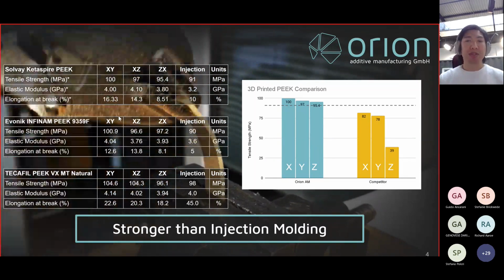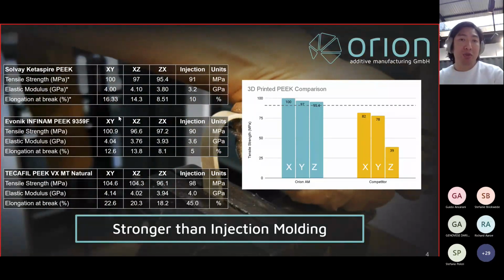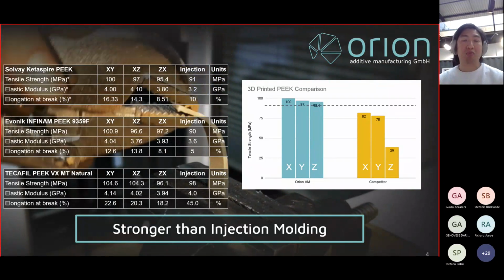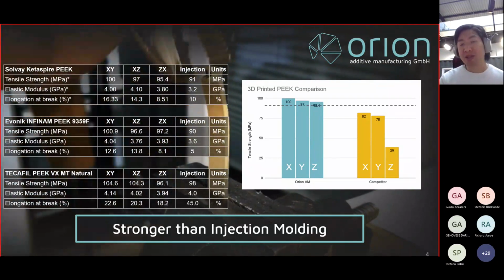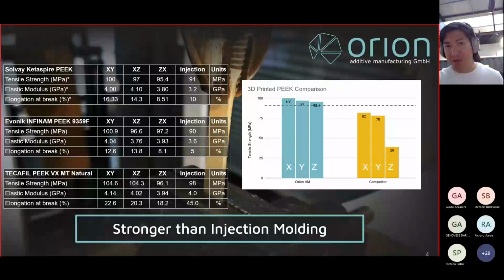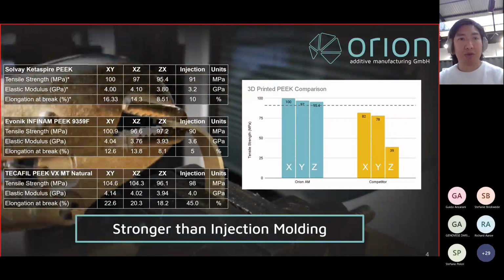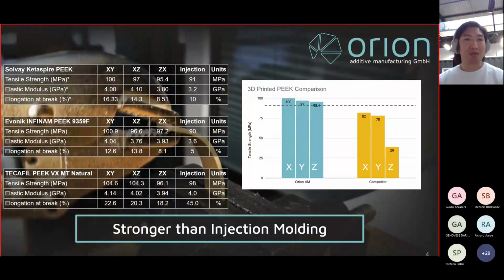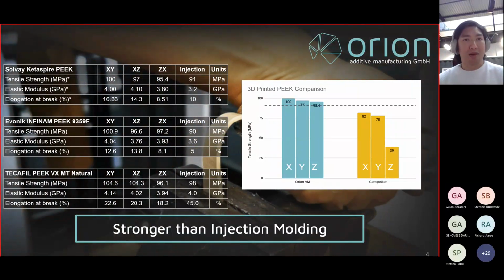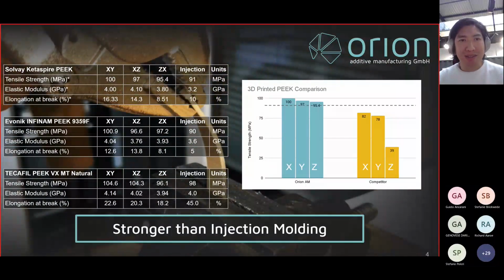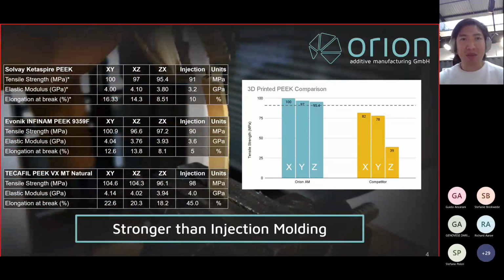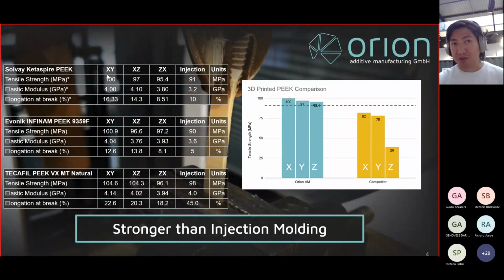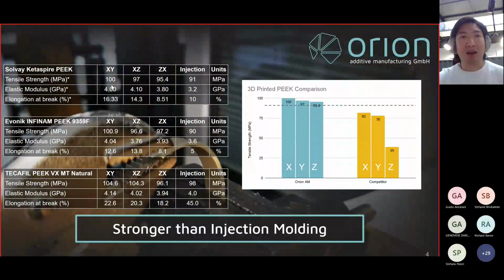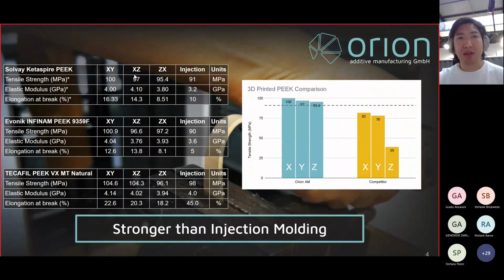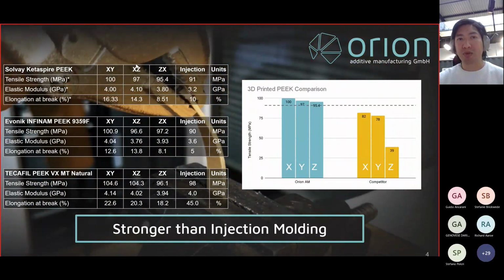We actually worked closely together with all the material suppliers to test the materials. We print them, we send them back the samples, and they test them in their own labs to make sure that it's validated using their own testing processes, and there's no biases there. So all across the board, in the flat orientation, which is fairly standard, it's already 10% higher than injection molding. This is the on edge orientation.